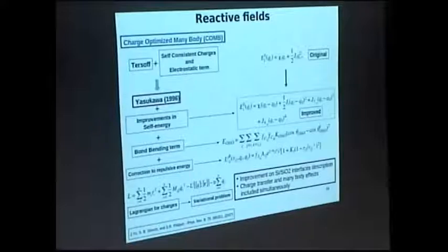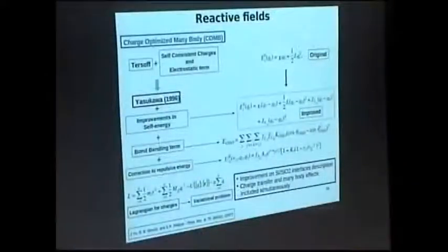The other way would be to make some kind of self-consistent calculation, in which you use initial charge and then substitute again and again in the equations. But usually this can take a long time also. Then this, despite the fact that in many articles, when you read, people ignore this part, sometimes is the biggest computational problem that we have.